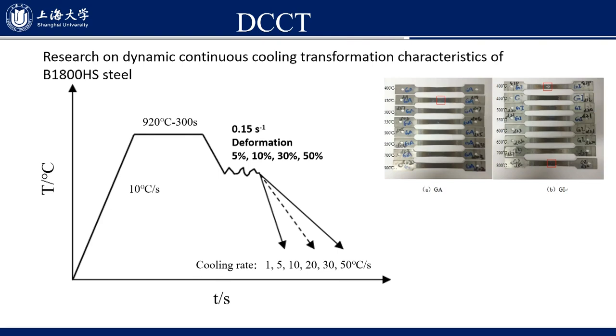Research on dynamic continuous cooling transformation characteristics of boron 1.8 gigapascal high strength steel is conducted on Gleeble with a dog bone type specimen as shown in this figure. The specimen was heated at 10 degrees per second to 920 degrees C, kept for 300 seconds, and cooled to the deformation temperature, deformed by 5%, 10%, 30%, and 50% with a strain rate of 0.15 per second, and then cooled with different cooling rates to room temperature.